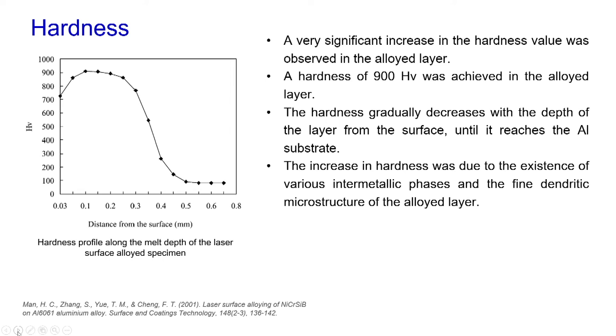The hardness was also recorded for the alloyed layer. Here you can notice that the x-axis is the distance from the surface, and the y-axis is the Vickers hardness. It has been noticed that a very significant increase in the hardness value is observed in the alloyed layer. As we move inside the workpiece along the thickness direction, the hardness is getting reduced.